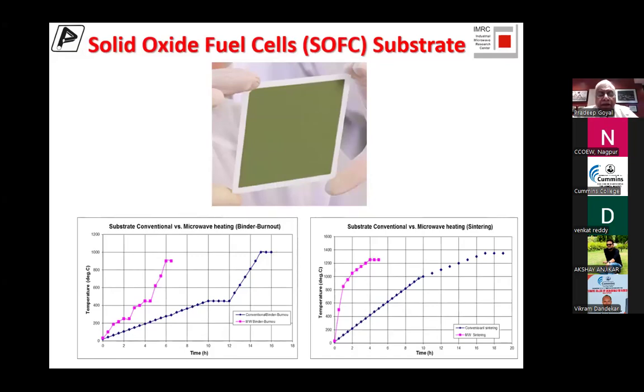You will see very clearly, if you look at the graphs underneath there, the pink graph shows you how fast we can do a certain process under microwave conditions to have a binder burnout compared to the conventional binder burnout process. You could see clearly that we could do it at a lower temperature, at about 900 degrees instead of 1000, and instead of 16 hours, we were able to do it in about 6.5 hours. So that's a huge amount of energy saving if you see that. So not only are we saving precious fuel, but we are doing it under electric conditions, and the energy consumption is considerably lower. Same thing if you see sintering, you'll see the same process, that it happens very rapidly.